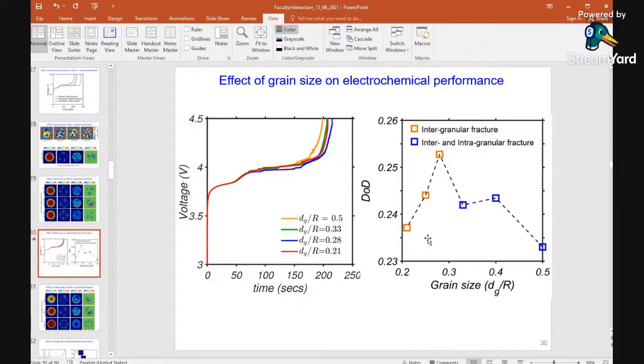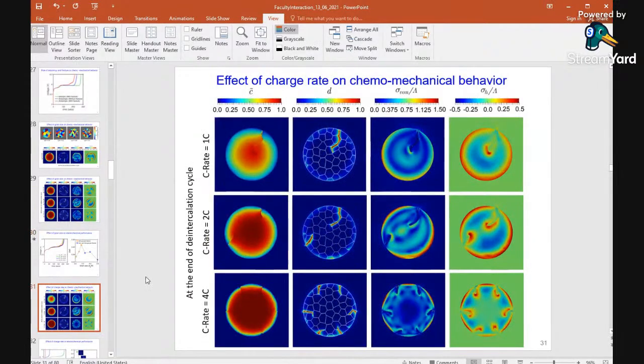We can see that only intergranular fracture is happening, so the crack is propagating through the grain boundaries. But in case of a higher grain size, we can have a mixture of fracture mechanisms. So that's the way we can map what type of fracture is happening. And then the next part we study here is the charge rate.